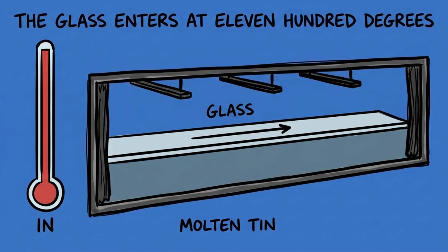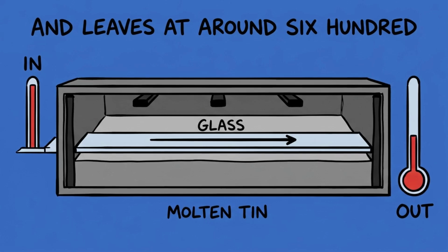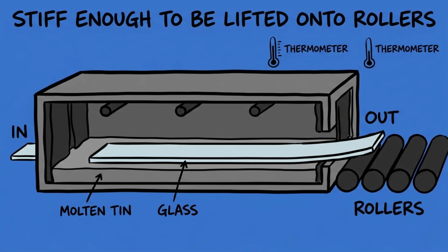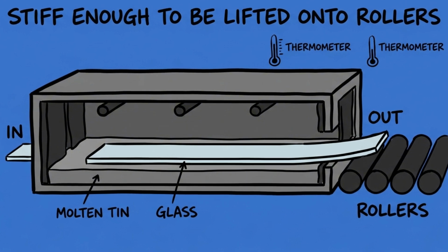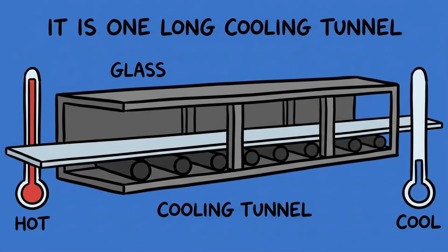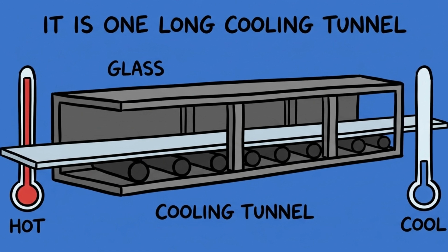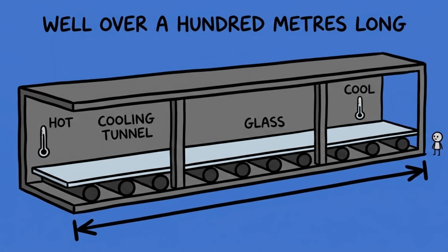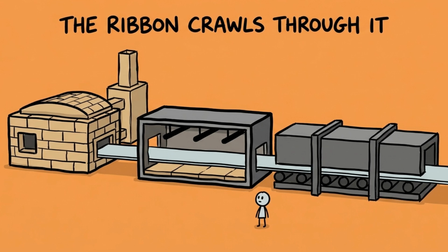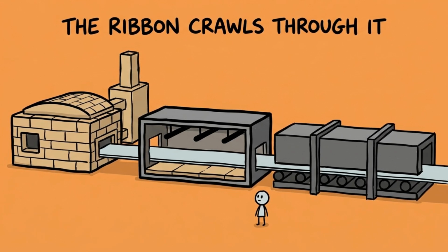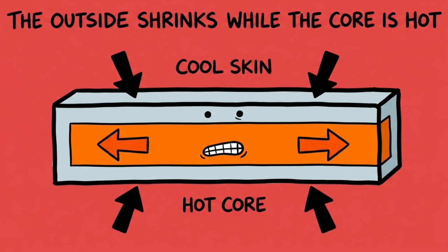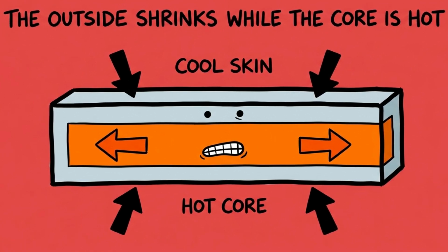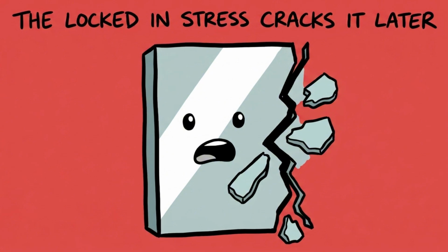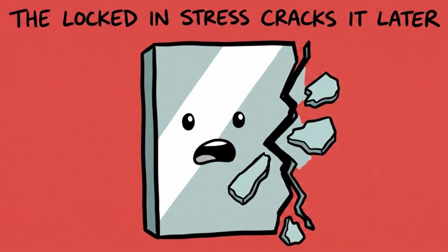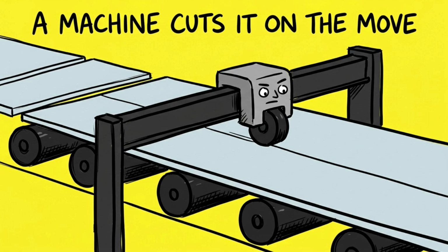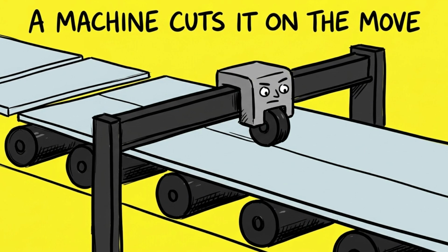The glass enters the tin at around 1100 degrees and leaves at around 600, by then stiff enough to be lifted onto rollers. Then it goes into the lehr. That is a cooling tunnel, and on a float line, it can run for well over 100 meters. The ribbon crawls through it while the temperature comes down slowly and evenly. Rush that step, and the outside contracts while the core is still hot. The stress locked into the sheet would crack it later, sometimes days later, sitting in a warehouse. At the far end, a machine cuts the moving ribbon on the fly.